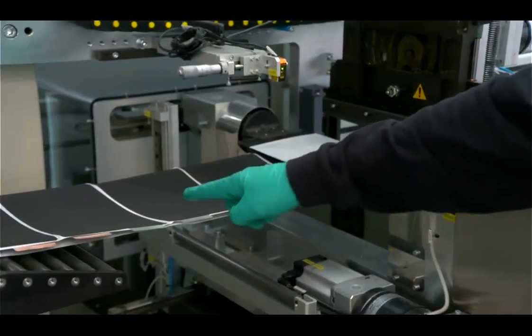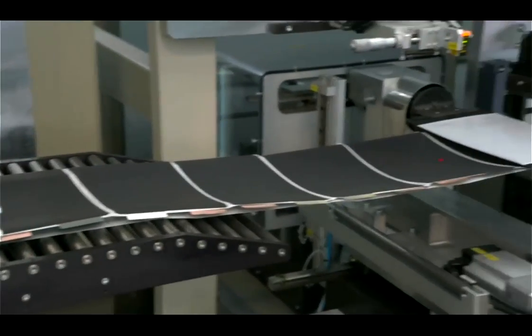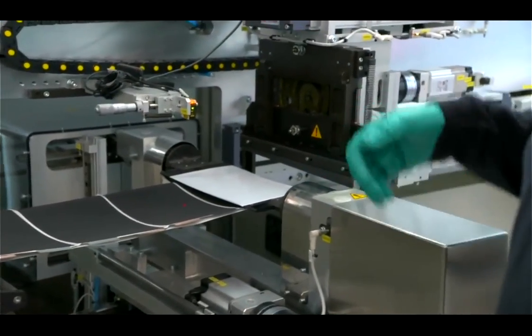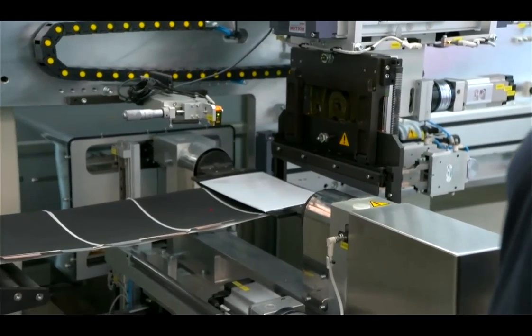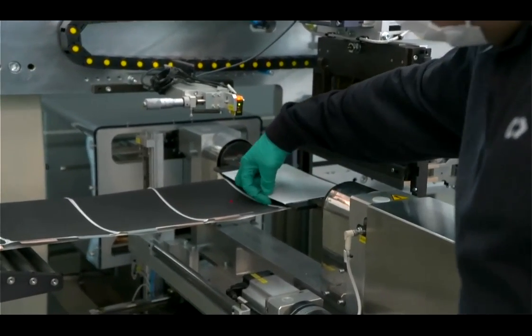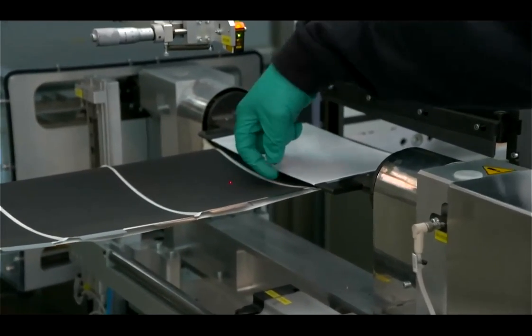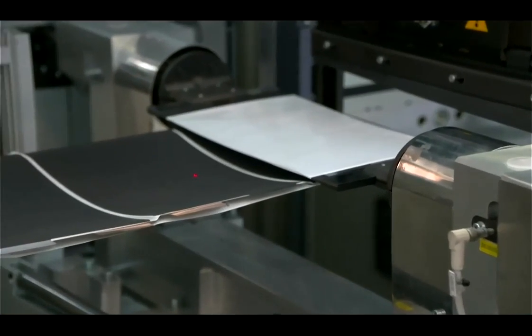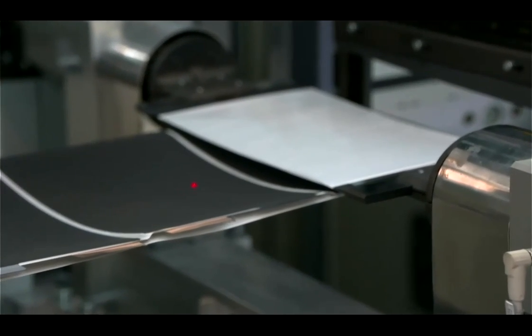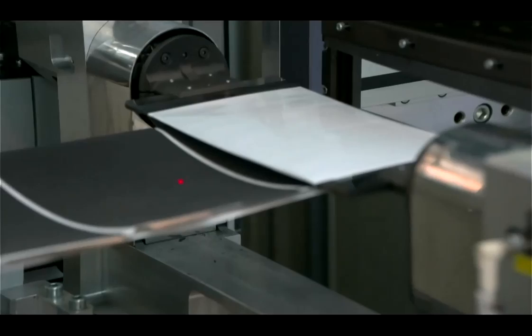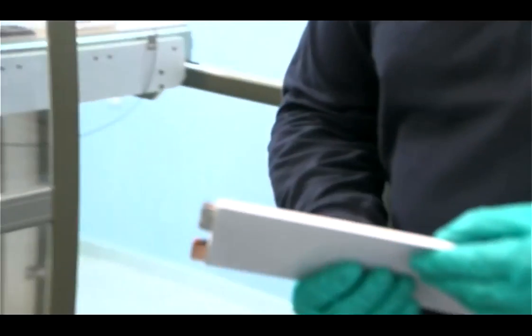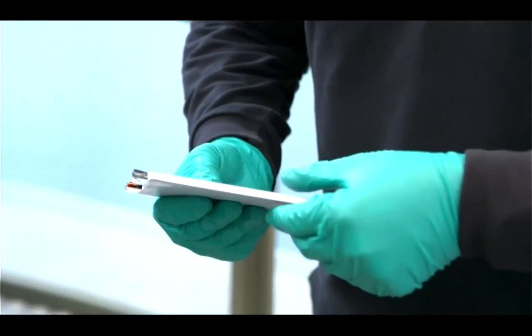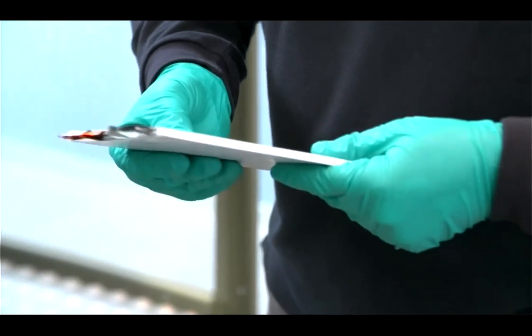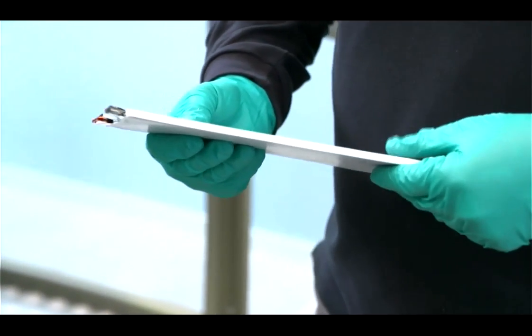And how is the distance, because the last electrodes are more separated than the first ones, because we have this small part of the separator that is just at the edge of both electrodes. So we have to set this for every stack. Of course, once we have one set of cells with the same chemistry and the same electrode design, it's already set and we can continuously run. And here are the edges that we were mentioning. Thank you, Iker.